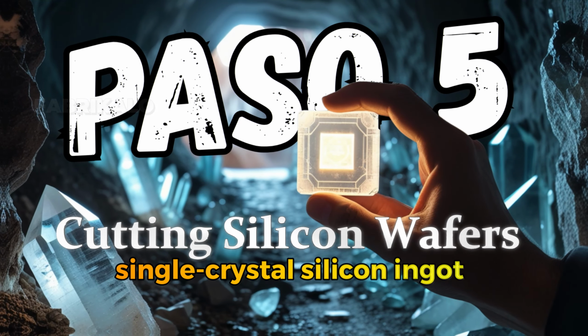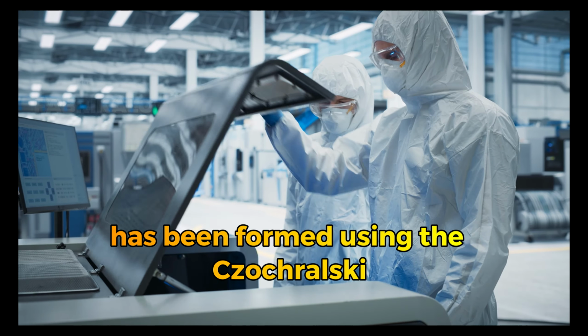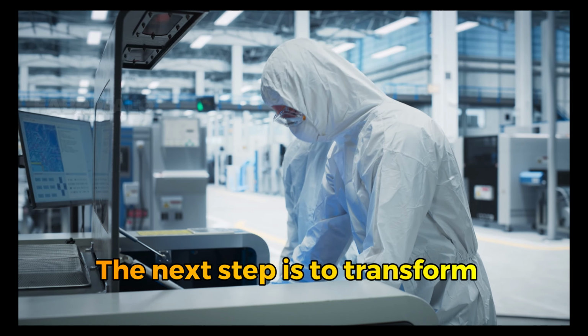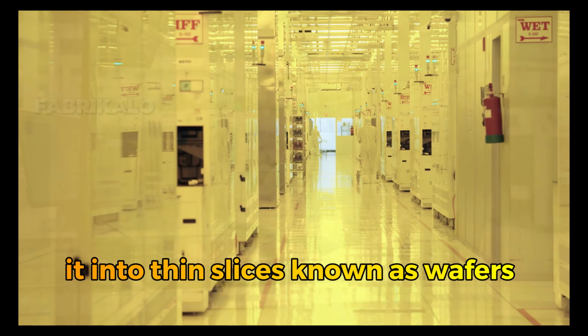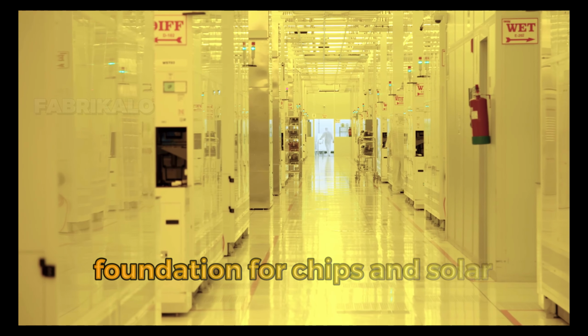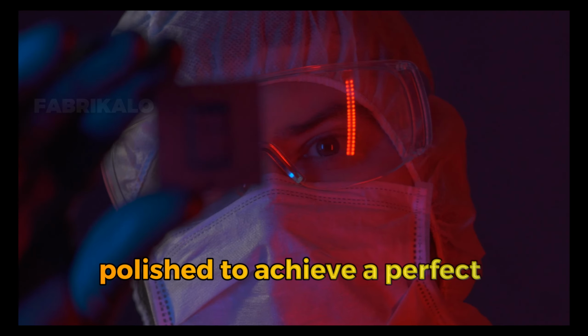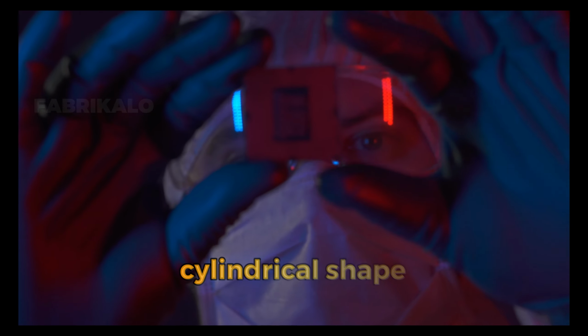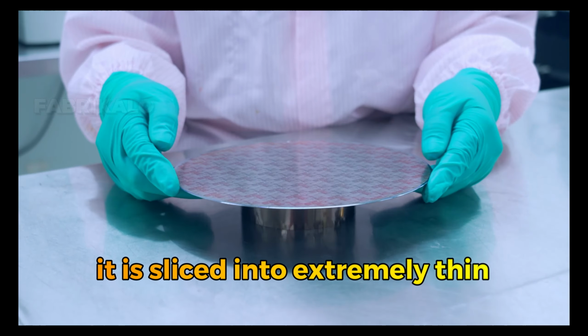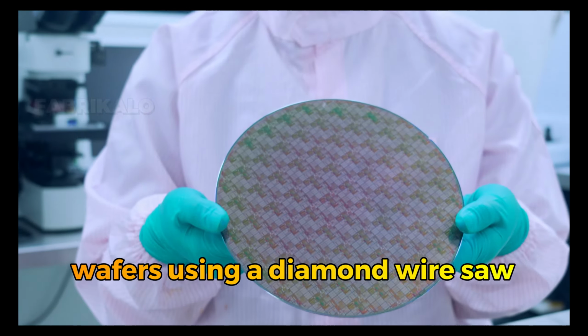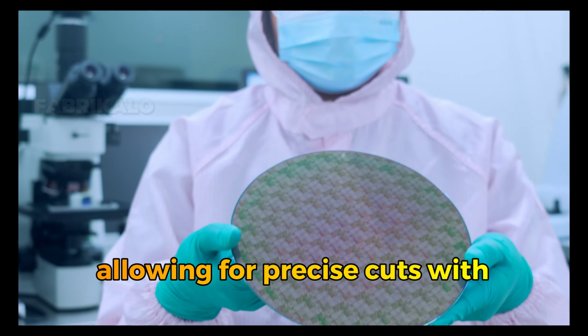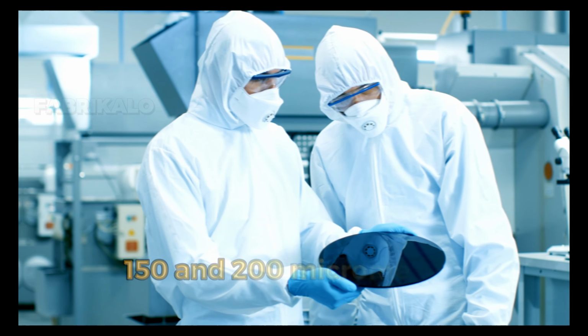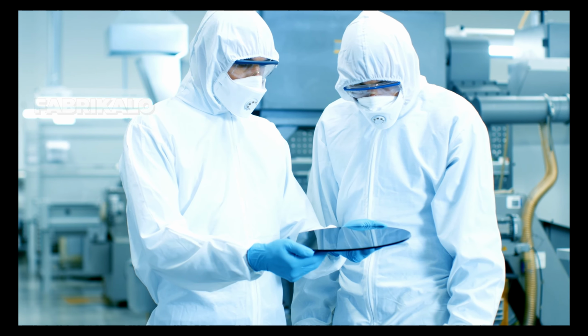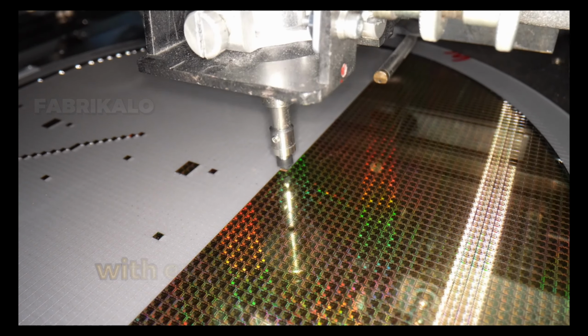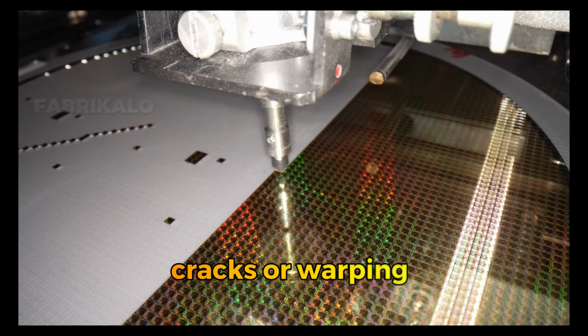Once the single crystal silicon ingot has been formed using the Czochralski method, the next step is to transform it into thin slices known as wafers, which will serve as the physical foundation for chips and solar cells. The ingot is first ground and polished to achieve a perfect, uniform cylindrical shape. Then, it is sliced into extremely thin wafers using a diamond wire saw, allowing for precise cuts with a thickness typically between 150 and 200 micrometers. This process must be performed with extreme care to prevent cracks or warping.